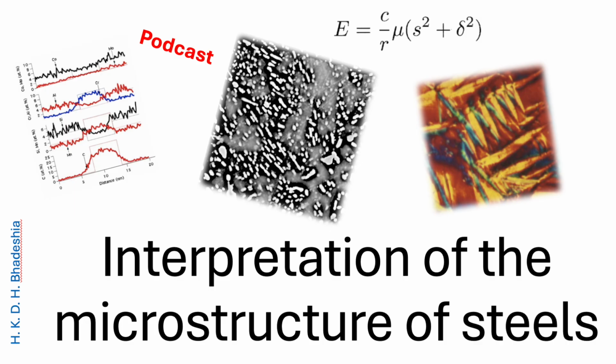There's zero change in chemical composition between the parent and the product. A one-to-one atomic correspondence is maintained. And that, by the way, is the basis for things like the shape memory effect. But there has to be a trade-off. Oh, a massive one. Forcing atoms to move in this disciplined way generates huge internal strain energy. And to minimize this energy, the phase absolutely must adopt a very specific shape, the thin plate.